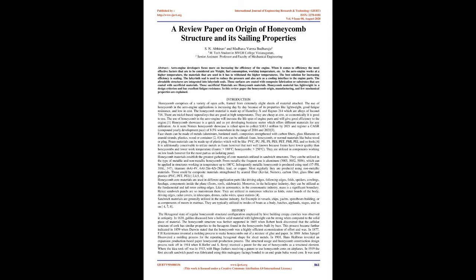higher temperatures. The best solution for increasing efficiency is sealing. The labyrinth seal is used to reduce the pressure and also acts as a cooling interface to the engine parts. The abradable structures are integrated into labyrinth seals. Those surfaces are coated with composite fabrication or substrates that are coated with sacrificial materials. Those sacrificial materials are honeycomb materials.